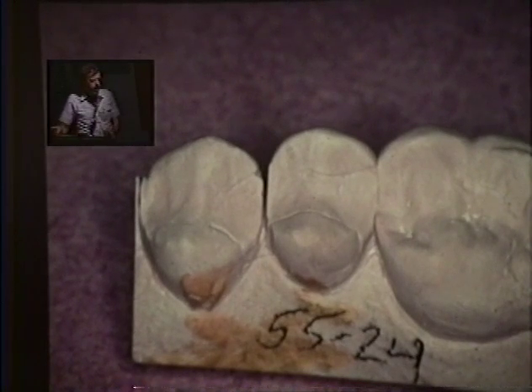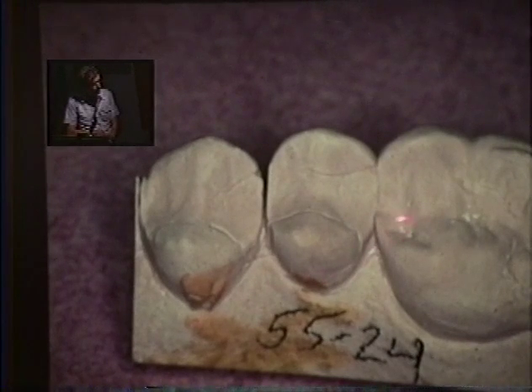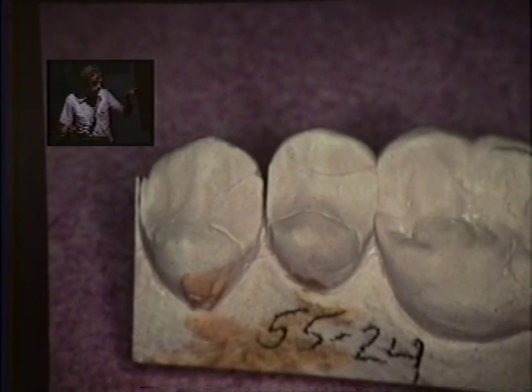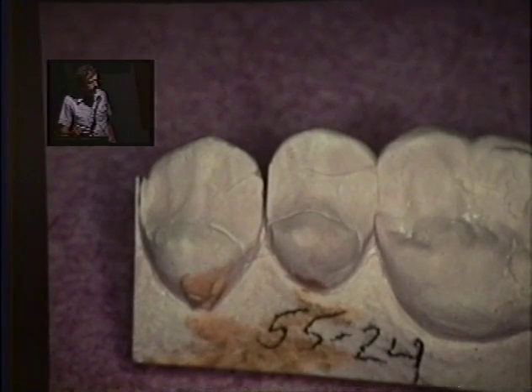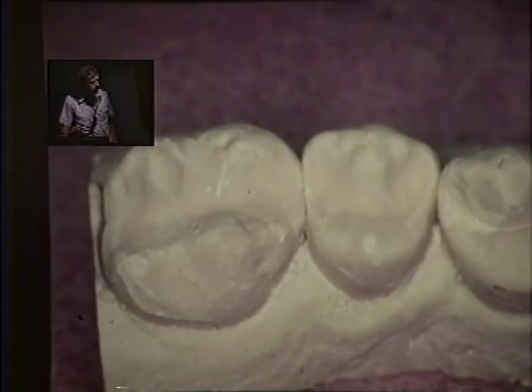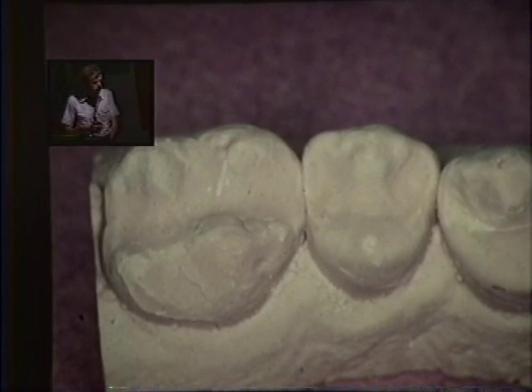Now, if we were to go back at placement time of that filling material there, re-etch the margins, okay, re-etch all the way around, and put in a penetrating sealant, one that would penetrate a very small defect that's even smaller than what you see there. Kind of like an occlusal sealant, except it isn't an occlusal sealant. It's a water viscosity penetrating resin. Here's the kind of result you can get. It's the same patient, the same ugly P50 at 2 years, and there's the margin. You can sort of see it there.